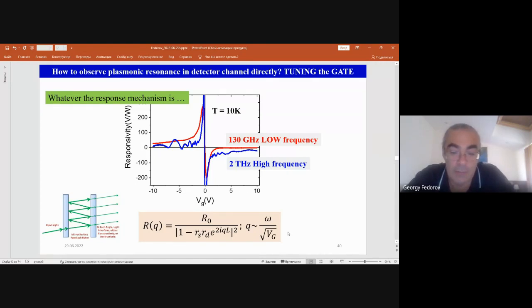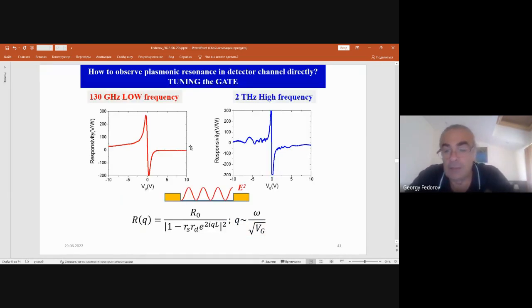We can approximate the response of this device with this ansatz, where R0 is this red line we obtained at low frequency. And this denominator describes a very well-known textbook optics expression for calculating transmission through the Fabry-Perot interferometer. So the RS and RD are reflection coefficients, which are small. They have to be about 1 for having a high-Q interferometer, but in our case they are small. So the oscillations are not very high amplitude, but still